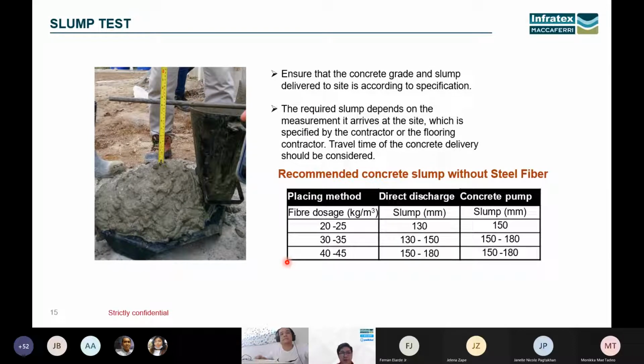Then simultaneously with the washout test, we can do slump tests. It would depend on the fiber dosage and on how you will discharge your concrete. For fiber dosage of 20 to 25 kg per cubic meter, if you do that by direct pouring, your slump must be 130 mm. If you're going to use a concrete pump, the slump must be 150 mm.